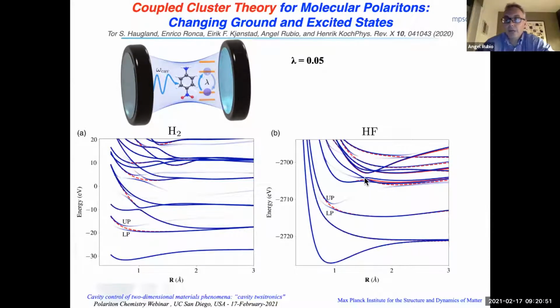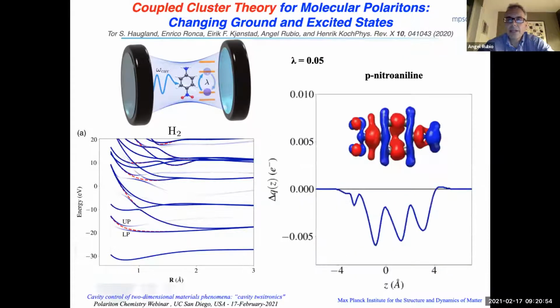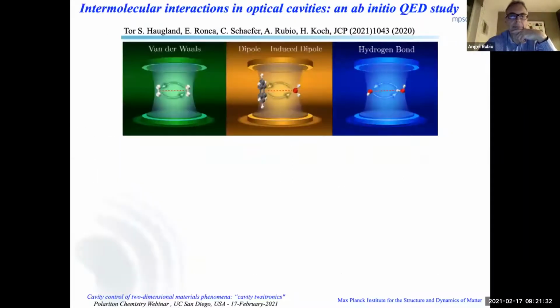hydrogen fluoride molecule. However, what I think is really important is that if you do it in another, bigger system, which is para-nitroaniline, you will see that in the cavity, when it's tuned to the HOMO-LUMO excitation, you see a change of the electronic density of the molecule in the ground state, which is of the order of magnitude of 10 to the minus 3 with respect to the molecule outside the cavity. This gives you solid ground that there is indeed this modification of the ground state, and then you have a playground to control chemical reactivity and the interactions of molecules, both in the ground state and in the excited states.